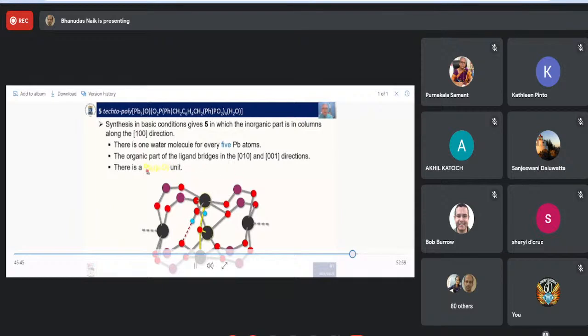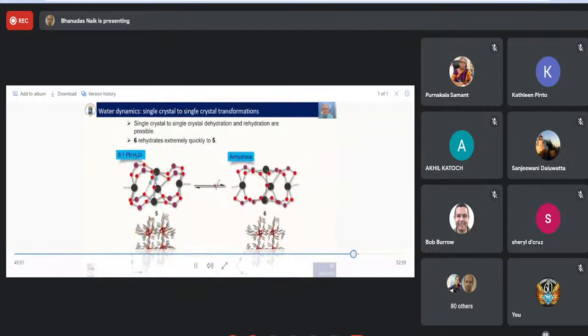And here you have the unit, which is highlighted so you can actually see it easier. And this compound as well, if you want to, you can dehydrate it and you form an anhydrous oxybridge compound, and this really quickly rehydrates back to 5. So this is compound 6. And this compound, we can do this on the diffractometer, just heating up this compound here with a hot stream. And you can see that as well as the other sequence of 1 to 4, it's extremely similar. You have the columns of the phosphonate bridged metal centers, and these are connected by the organic ligand spacers here.